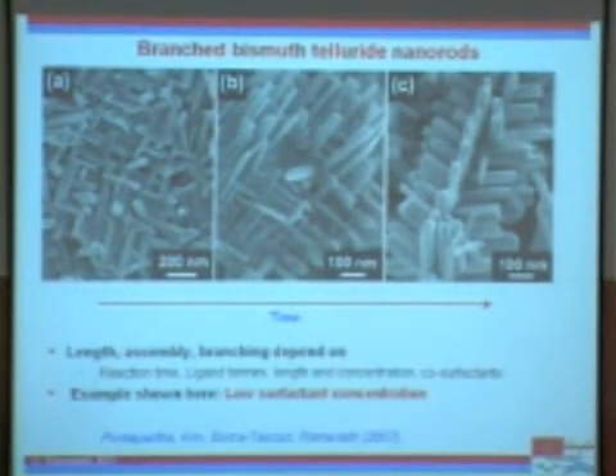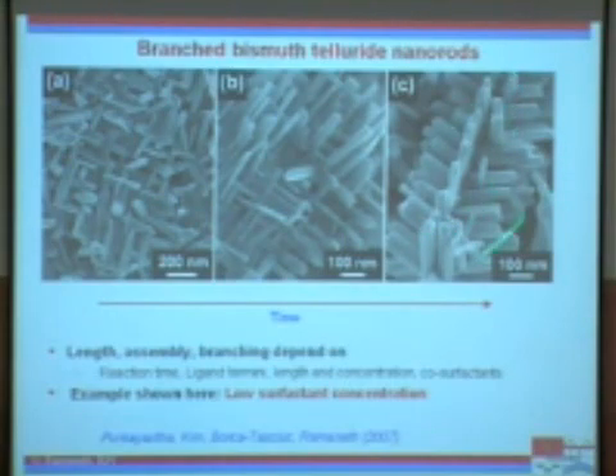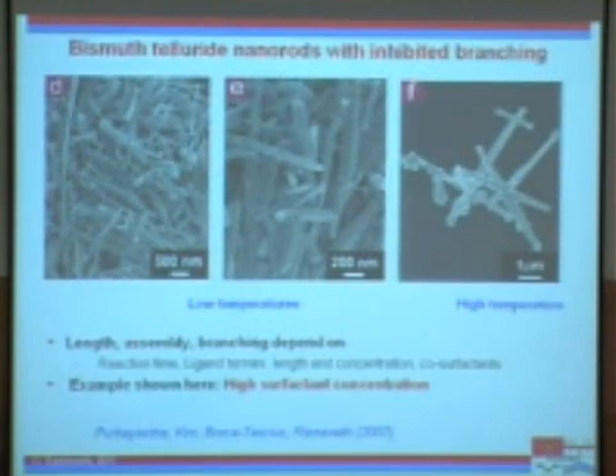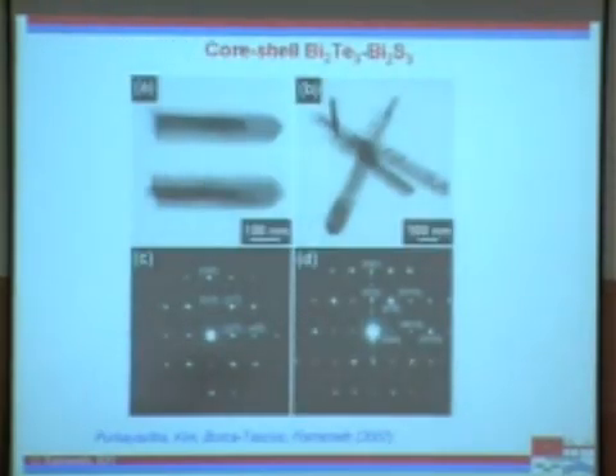Okay, we can make complex architectures of these as well. So these are not unlike what I showed you in the case of carbon nanotubes, but the methods used are completely different. You can see that I can control the degree of branching, and everything here is a single crystal. These are all modulated by using molecular templating agents. And this kind of control would be very useful to make architectures where, let's say this is a hot spot, I want to carry heat away in various different directions. You can think about designing these kinds of thermal conduits. I'm going to skip the mechanism part of it because that's probably not too relevant.